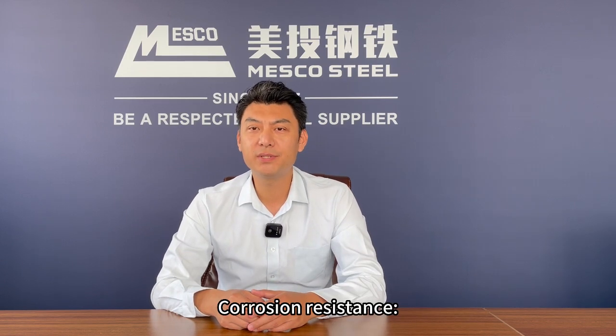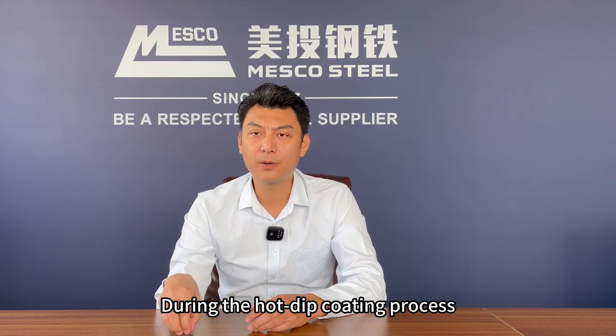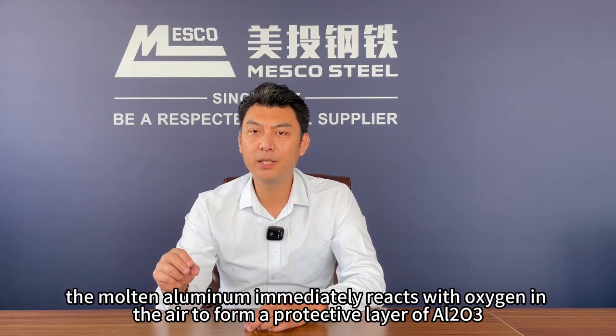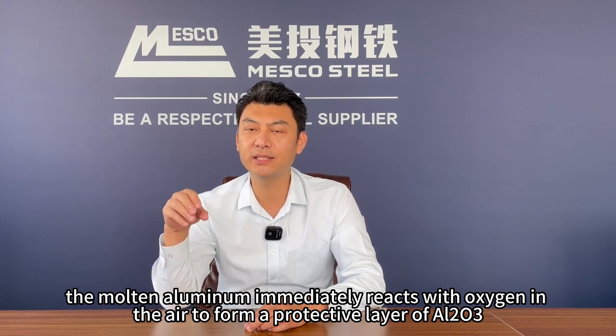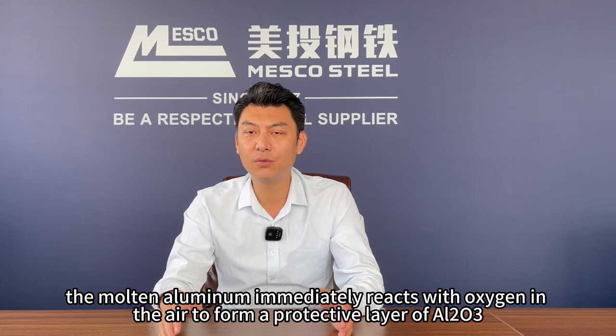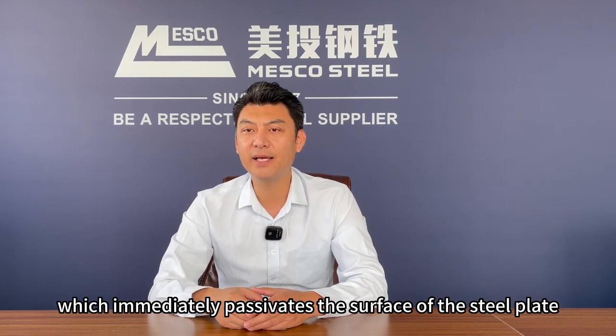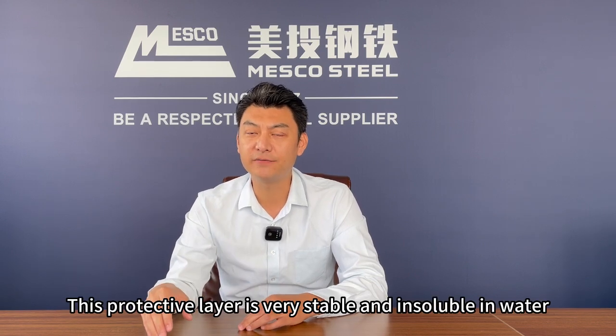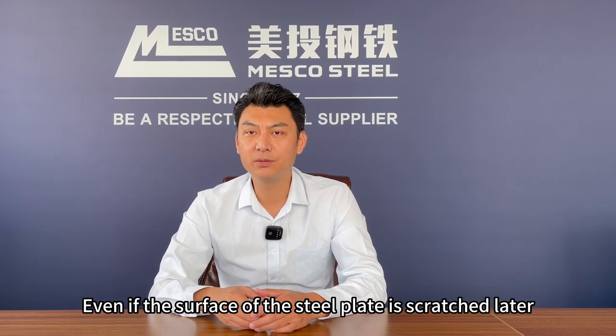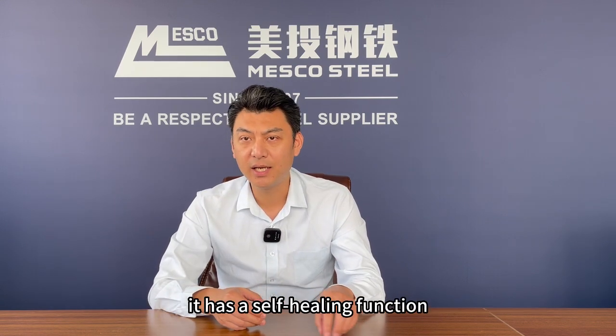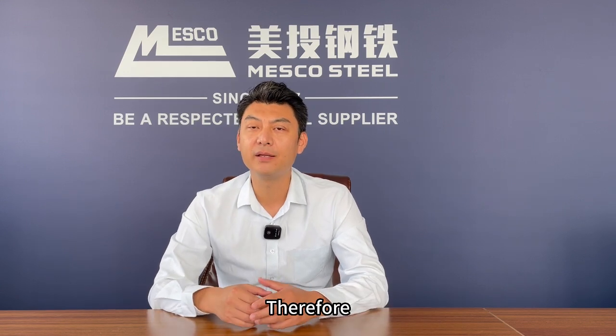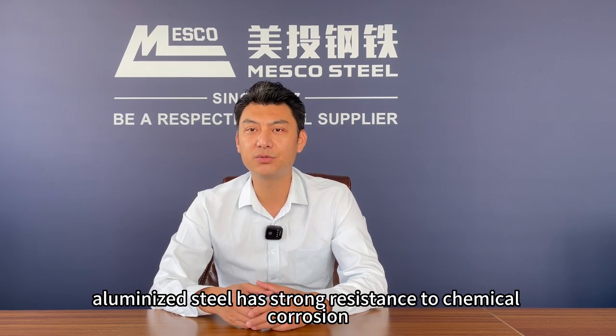4. Corrosion resistance. During the hot dip coating process, the molten aluminum immediately reacts with the oxygen in the air to form a protective layer of Al2O3, which immediately passivates the surface of the steel plate. This protective layer is very stable and insoluble in water. Even if the surface of the steel plate is scratched later, it has a self-healing function. Therefore, aluminized steel has strong resistance to chemical corrosion.